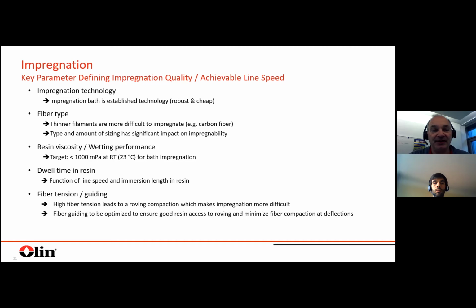The fiber tension and guiding, it's often not considered. So if you have, for example, a high tension tow, it also closes the tow, makes impregnation more difficult. But also the fiber guiding of these tows has to be optimized so that it has a good access. So if you bundle a few rovings and guide them through a bath, the inner rovings don't have access to the resin, so the wetting will be bad. So a more homogeneous distribution could be helpful. Spreading, for sure, is also important, to flatten it so that there's better access. So everything which is related to fiber guiding, tensioning, directly impacts impregnation capability.